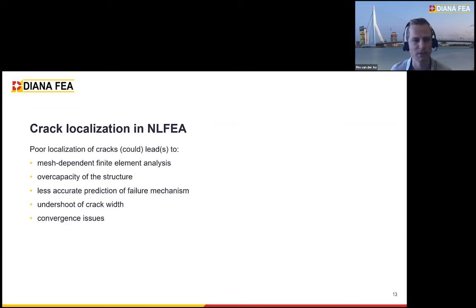In the second part of the presentation, we're going to talk about crack localization in nonlinear finite element analysis and why it is important. What will happen if you have poor localization of your cracks? This could lead to a mesh-dependent finite element analysis. You could get an overcapacity of the structure. It's less accurate how you can predict your failure mechanism. And mainly you undershoot your crack width and you could face some convergence issues.